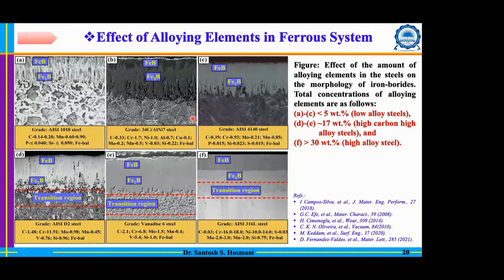Another interesting thing is that if you go through the literature, you realize that different morphologies of these iron borides are shown by different authors. Here you can see on the screen figures A to C. These are related to steels having alloying element concentration less than 5%. Then you go to figures D and E, which have a concentration of about 17 weight%, and F has a very high concentration, greater than 30 weight%.